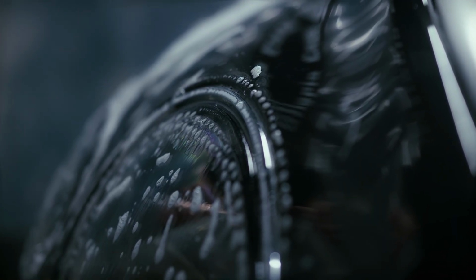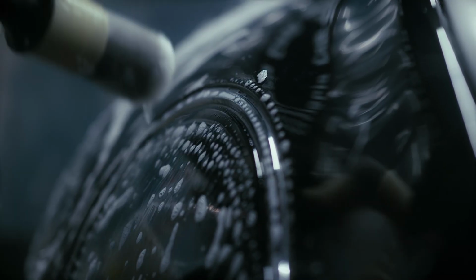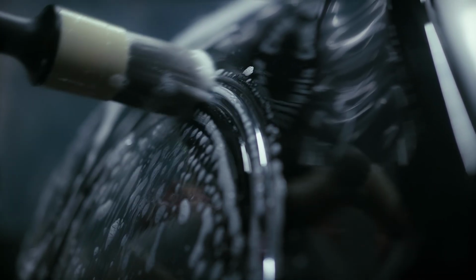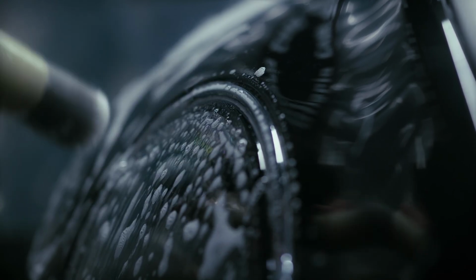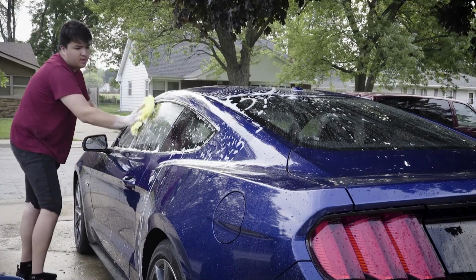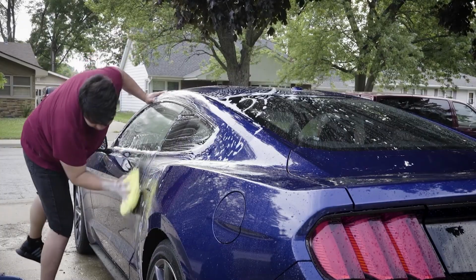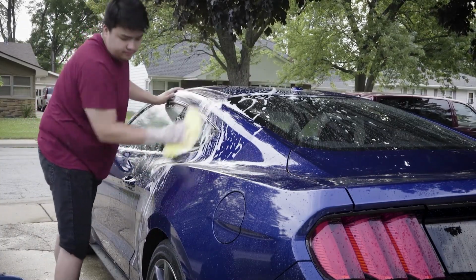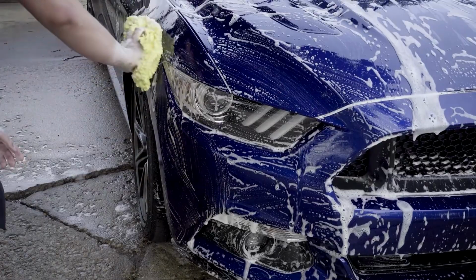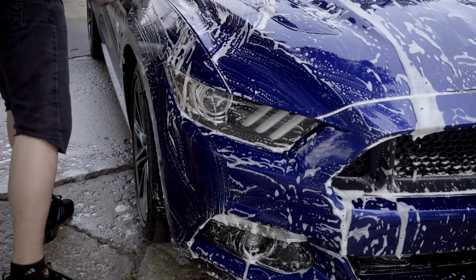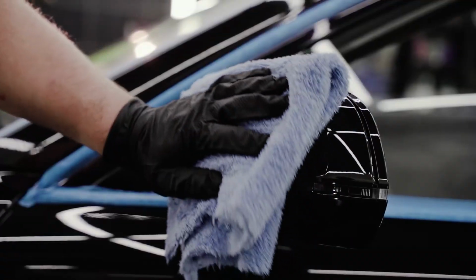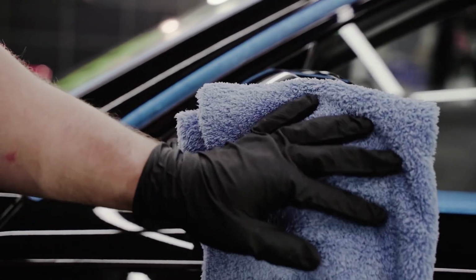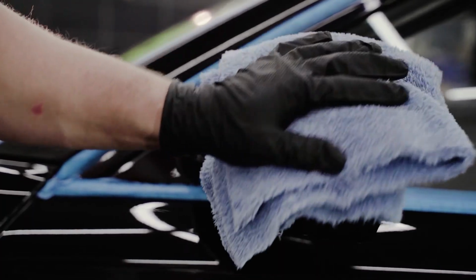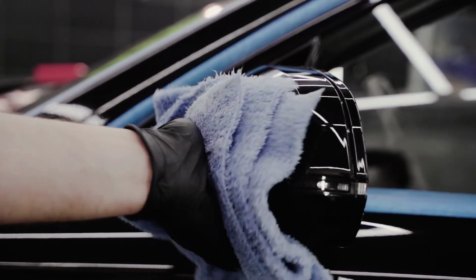In the precision workshops in Stuttgart, the use of repellent is considered the kiss of death for an optic. Once the chemical evaporates, the plastic remains extremely weakened. Additionally, the oily residue of the repellent attracts the road dust, which embeds in the still soft plastic, creating a natural sandpaper that will destroy the headlight in a matter of days. Worse still, if the spray touches the rubber gaskets that seal the headlight, it will degrade them, allowing the entry of humidity. What started like a trick of 10 seconds will end costing you the complete replacement of the optical unit, which in modern cars with LED technology can ascend to thousands of euros. It is a chemical trap from which there is no easy return.